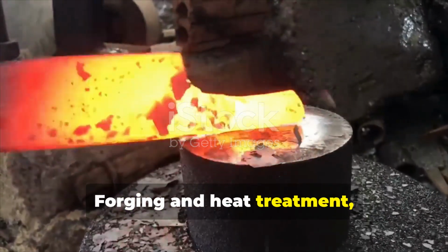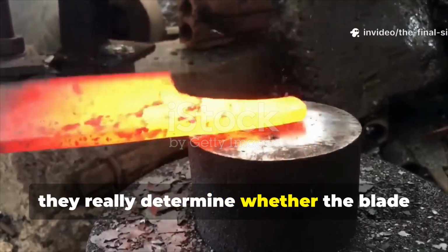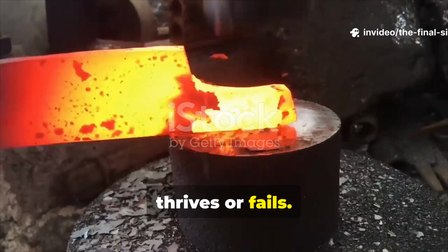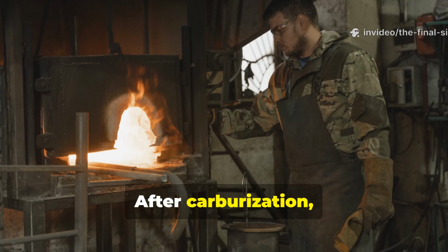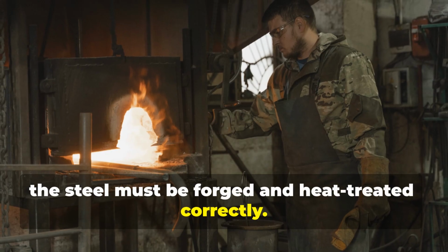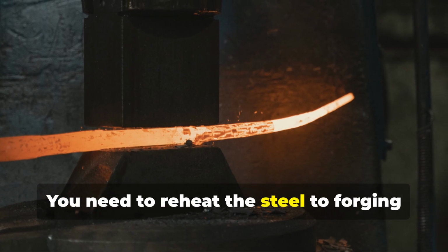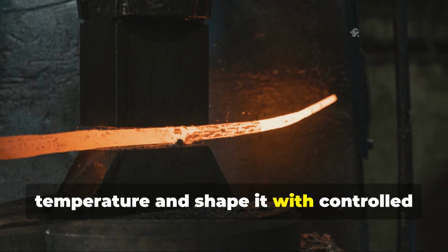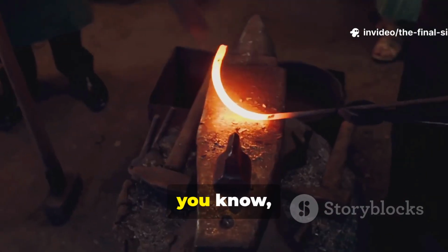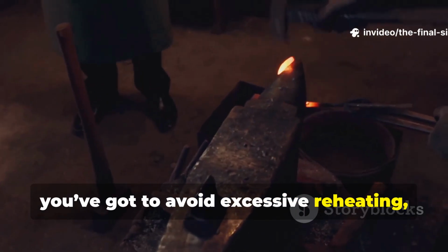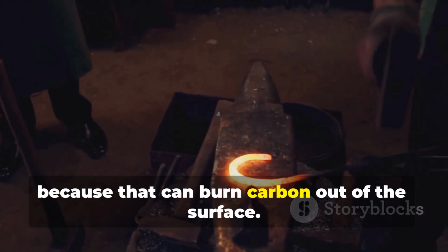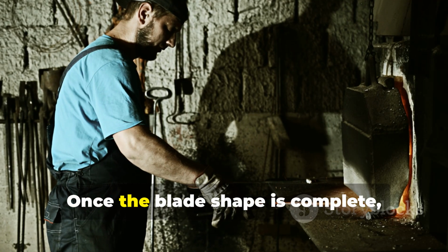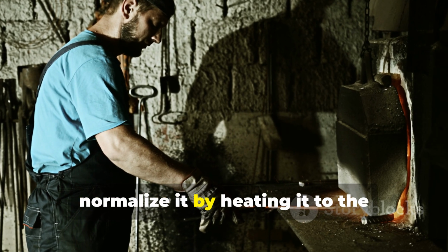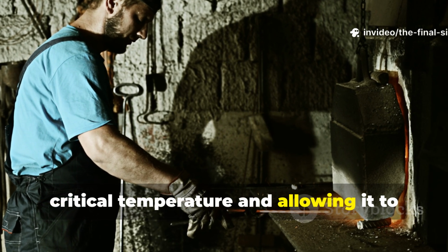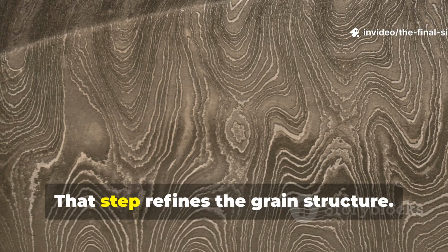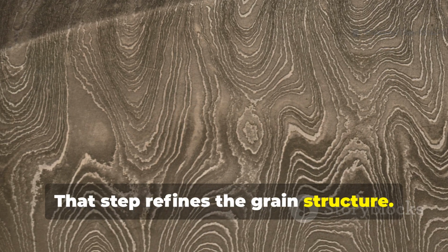Forging and heat treatment really determine whether the blade thrives or fails. After carburization, the steel must be forged and heat-treated correctly. You need to reheat the steel to forging temperature and shape it with controlled hammer blows. But you've got to avoid excessive reheating because that can burn carbon out of the surface. Once the blade shape is complete, normalize it by heating it to the critical temperature and allowing it to air cool. That step refines the grain structure.